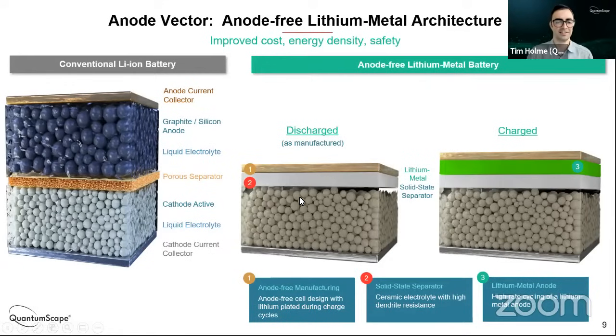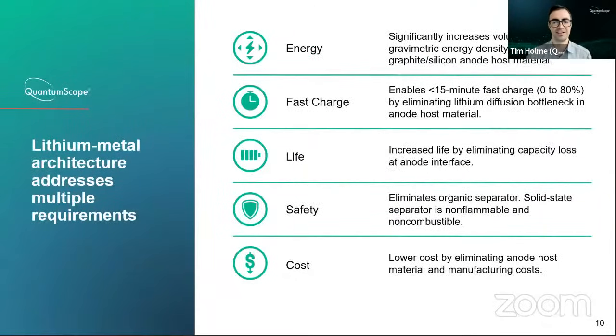One thing that you can see from these schematics, which are drawn roughly to scale, is that by eliminating the anode host material, you make a meaningful improvement in the energy per volume of the battery. That also translates to energy per mass to some extent. But you not only improve in energy density, you can also improve in a lot of the other metrics that are really important to an EV driver or a battery consumer. Fast charge: by eliminating the lithium diffusion bottleneck into the anode host material, you can enable faster charging. It also turns out that the anode is responsible for one of the main degradation mechanisms in a battery. The reason your phone doesn't last as long today as when you bought it is in part due to the fact that the anode on every cycle can crack some of the protective layers that form around it, which then have to reform, consuming electrons and lithium from the cell. By eliminating that failure mode, you can also improve the life of the cell.